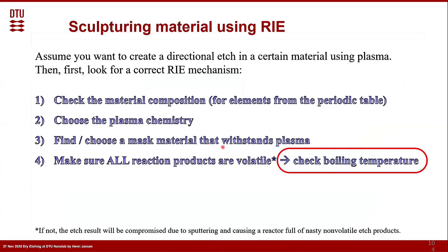Okay, now we would like to sculpture. So we would like to etch inside our reactor, and we would like to create a directional etch with a certain material. Then the first thing we have to do is look at the correct reactive ion etch mechanism. That means, first of all, check the material composition, so the elements from the periodic table we just saw. Based on that, we have to choose a plasma chemistry. It can be fluorine, bromine, or maybe even carbon monoxide. Then we choose a mask material that can withstand this plasma too, because we need to sculpture it and something has to withstand it on top to make our device.